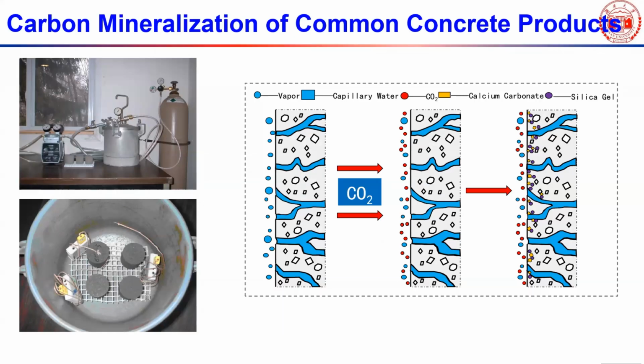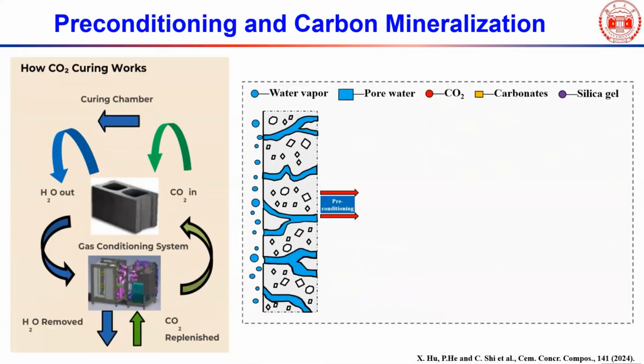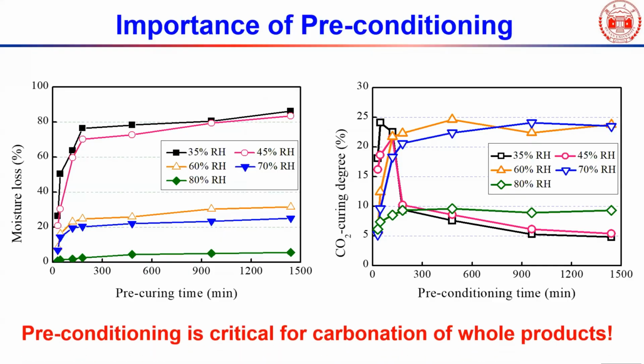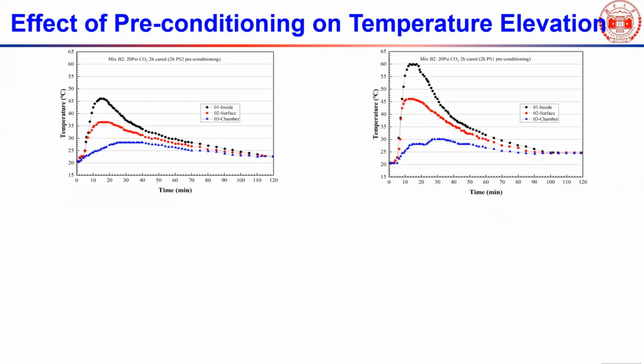If you look at the CO2 curing chamber, you can see 3 temperature sensors. One is inside, in the center of the sample, one is on the outside surface of the sample, and one is on the surface inside the chamber. Then here is the recorded temperature. The black line is inside of the sample, the red line is the surface of the sample, and the blue line is basically inside the curing chamber.